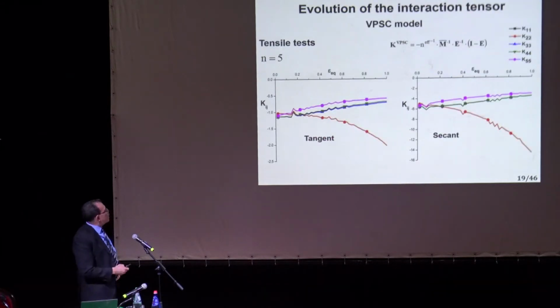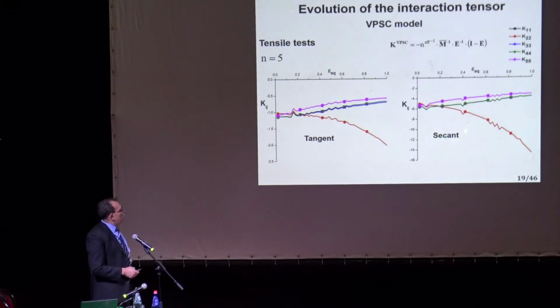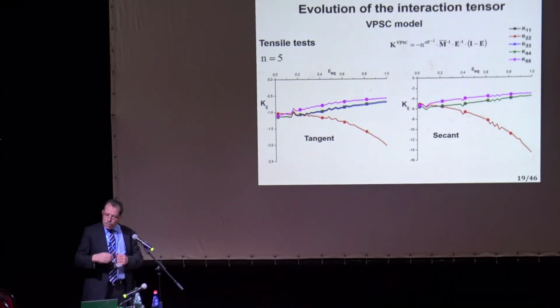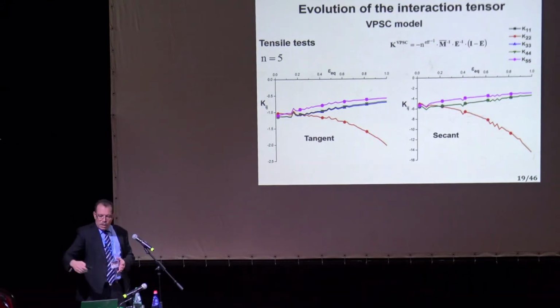If we go to self-consistent, it's the same thing. We use the tangent formulation that we developed in '87, and the secant formulation that Lebensohn and Tomé proposed in 1993. But there is an old paper, in fact, from 1965, where John Hutchinson from Harvard developed the secant already at that time, but it was not for large deformation. There was orientation in it, but no texture prediction.